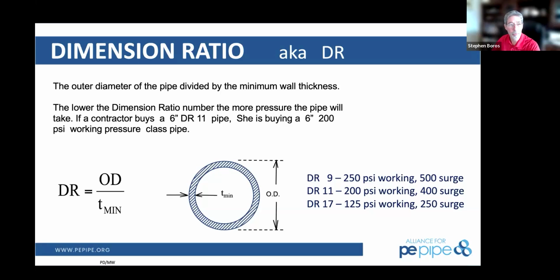That means you can flow probably in the range of around 10 to 12 feet per second, and you would not surpass these surge allowances that polyethylene has built into it. Other materials, depending on the way their pressure class is defined, and every material is different. Every AWWA standard designs pressure class differently for ductile iron, PVC, and polyethylene. You will have to derate that product if you have surge going on in your system. Depending on the material, it's going to be different. So it's up to every design engineer to understand that and to derate their product if they do have those limitations. Polyethylene doesn't have that limitation. So whatever the working pressure rating is, you have all this surge capacity above that without having to derate.